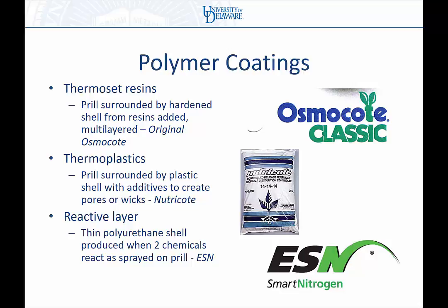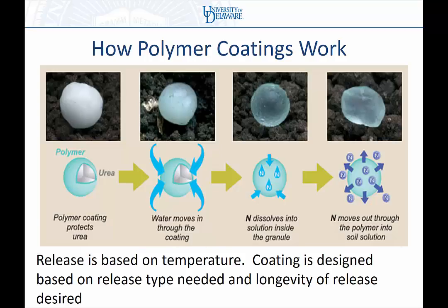All right, but this is where your products like ESN and the technology that they use come in. And how these coatings work is that the shell has a permeability somewhat. There are some pores that allow water in. That water dissolves the fertilizer that's inside the granule, and because of osmotic conditions, it's a higher concentration inside than outside, so the nutrients diffuse out into the soil solution.